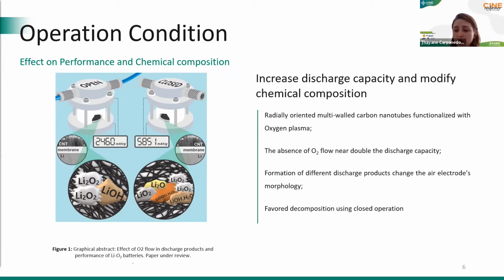And comparing the two setups, the operation condition called closed showed the best discharge capacity. It was possible to achieve nearly double the discharge capacity. And we also verified the formation of different chemical discharge products based on the operation condition. Besides, the chemical composition of discharge products, including the lithium hydroxide formation in the closed system, decreased the charge potential, favoring the charge process.